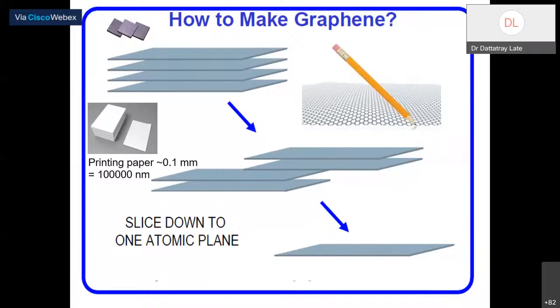This is a very simple thing. You just get the graphite crystal, and of course I need a very high quality crystal if I want very good layers of graphene. How much is the thickness of this printing paper in front of you? Printing paper thickness is 0.1 millimeter, which if you convert it into nanometer is 1 lakh nanometer, right? So I just want to slice down to one atomic plane of graphene.